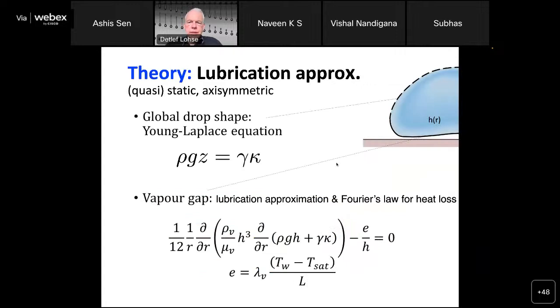And what we do is that for the droplet, we simply put in the global droplet shape, which is given by the Young-Laplace equation here, with gravity playing a role. So gravity is compensated by capillarity. And then we have a lubrication approximation for this layer under the droplet. That's the standard approach here. But what we have to add is this Fourier law for the heat loss towards the substrate. So that we couple.